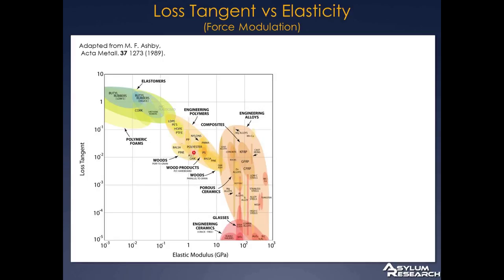As we go through the polymers, they get softer, so they range from maybe 100 gigapascal down to the megapascal range, so polymers and wood and things like that. And then as we get into the elastomers, the rubbers, and some kinds of foams, the stiffness goes way down and the loss tangent goes way up. So maybe one of these butyl rubbers, if you drop that on the floor, it doesn't ring nicely. It makes more of a splat sound.